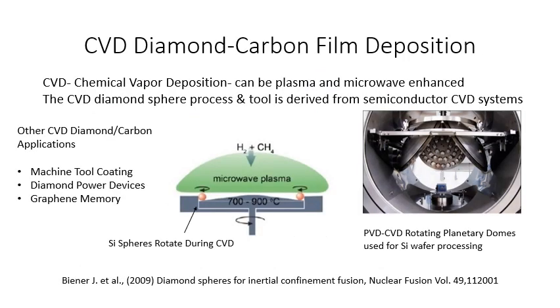So one interesting step is coating this polished silicon sphere with diamond. Just like we had to have a special piece of tooling to polish the silicon spheres, you have to have a special piece of tooling to uniformly coat the spheres with diamond. And this is done with a process called chemical vapor deposition. Again, this borrows and leverages tooling that was made for coating silicon wafers, which is shown on the far right. This is called a planetary rotating deposition system.